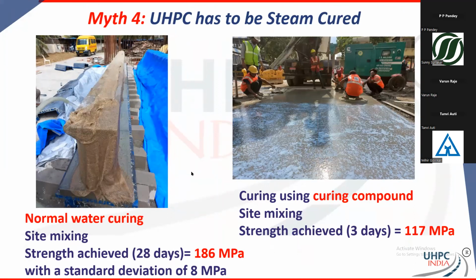I'm just going to move forward to the next slide. Curing. You absolutely don't need steam curing. You can do steam curing, but you don't need it. You can do water curing. You can also use curing compound, right? So here you see this was on site with water curing, 28 days average strength over a period of 30 days of casting, with so many cubes, 186 MPa average on site with a standard deviation of 8 MPa.